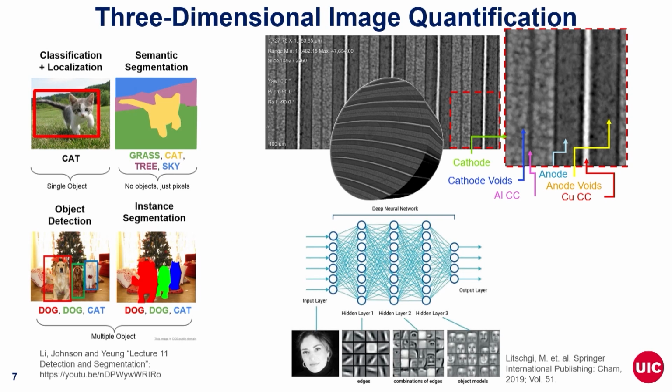So what we're looking at here is our cathode composite. So this is your secondary cathode materials with your conductive binder matrix. And then we're analyzing these cathode voids, so the voids that have formed within the conductive binder matrix. We found these voids in comparison to the as received or uncycled data. And then we have our aluminum current collector sandwiched between these two cathode composites. And then our anode structure, which is darker here, our graphite structure, and then the anode voids, as well as our really bright copper current collector.